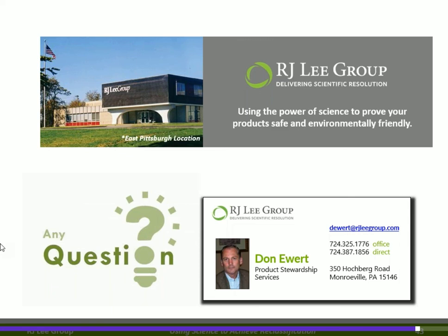The XRD with that high sensitivity is obviously a more expensive method, and the CCSEM with IntelliSEM is unique in that we've set the criteria from a toxicological perspective, and so that too takes a lot longer to run. So all the things we do, when you get into the Raman and CCSEM inter-instrumental, that can run into the many thousands of dollars. So easily our average project is around $1,500 to $3,000.